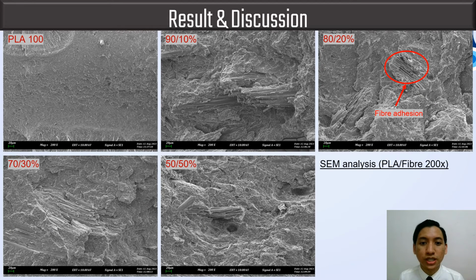Okay, this part shows the SEM photos of the fracture surface of PLA blends with various compositions of natural fiber. From the photos, it reveals that the fibers are not in loose form but in bundle form, which is embedded in the PLA matrix. The photo also shows bundles of fiber protruded from the matrix in the 90-10% and 70-30% blends, and we can see the track of bundled fibers as shown in the 80-20% blend.